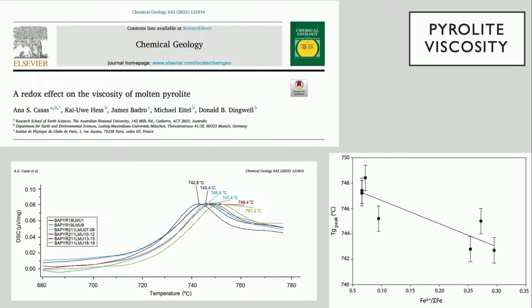So recently we've been doing this on extreme compositions, and what you see here is the precision with which we can obtain the difference in glass transition temperature, and you can see it here, 742.8, 745.4. These are extremely precise determinations of the glass relaxation time, and these are a function of the oxidation state of iron in a very, very low silica liquid.